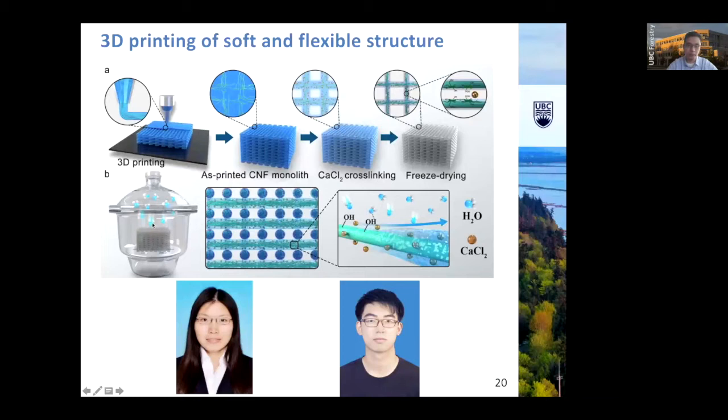After that, we can saturate this material in different environments with different relative humidity, and then it will have a water layer, and that water layer will trigger the elasticity of the material. This is because water can serve as a plasticizer for cellulose and for wood. For example, if you have a piece of wood and you saturate it with water, it will become soft and more elastic.